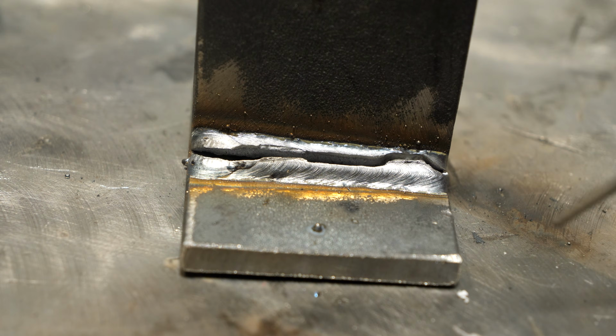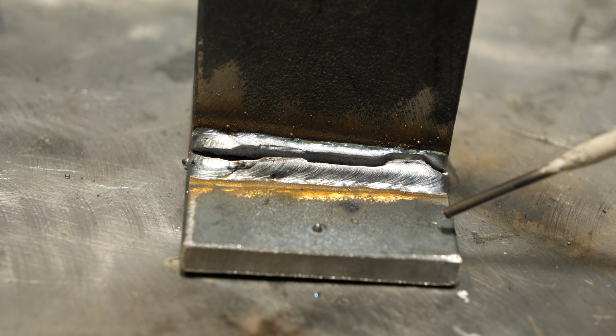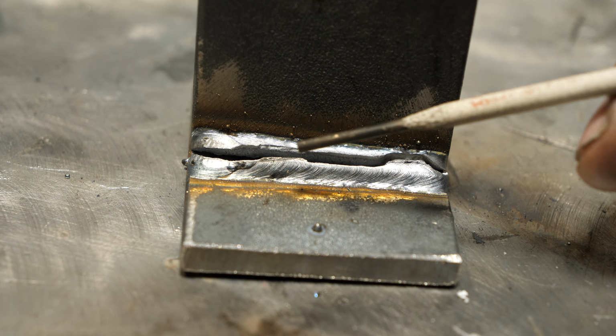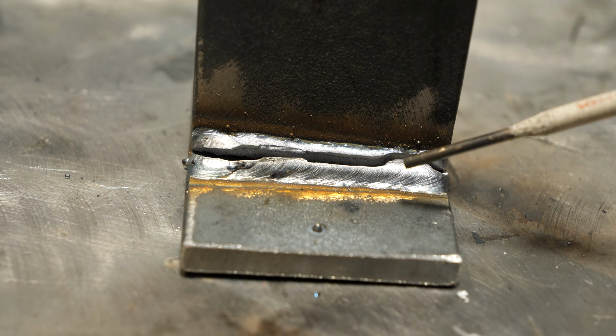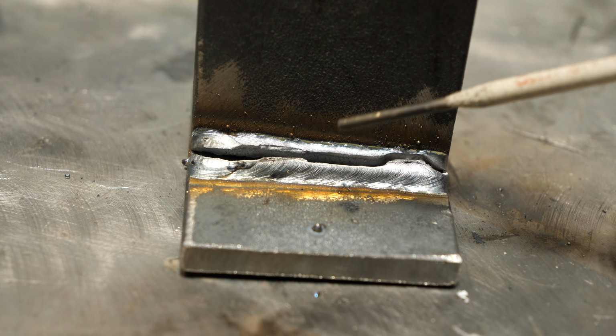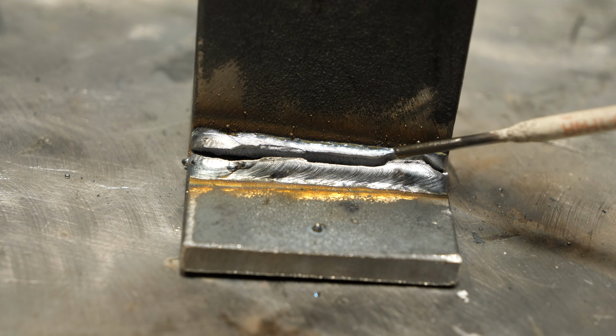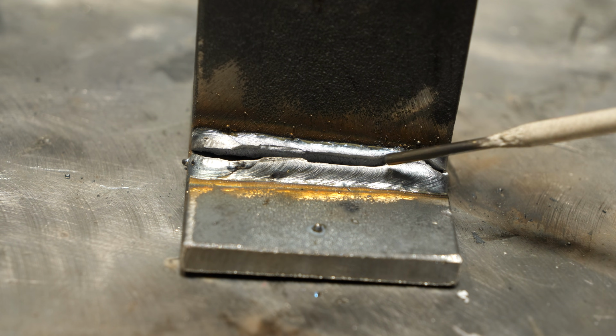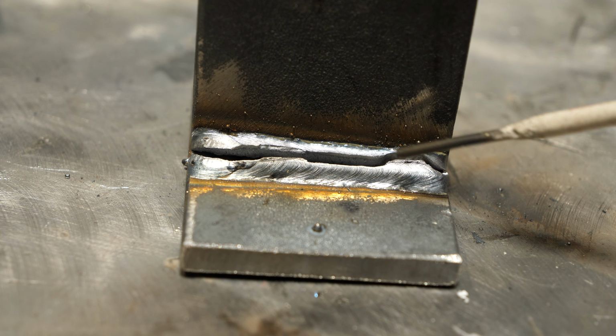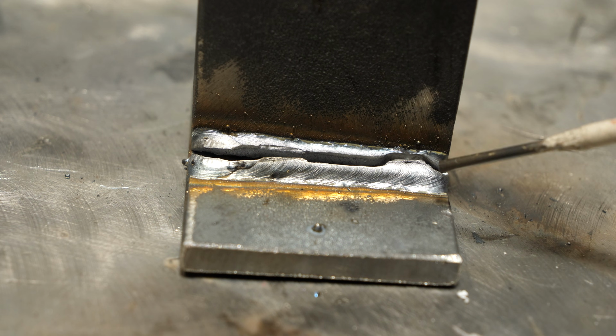Now let's look at the push. All right, so here's the push angle plate, and you can see better performance. The weld more or less broke down the middle of the plate instead of off of one side. And you can see this here where it broke off of this top plate. And if you've watched any of my videos, you probably already understand why. But this has a lot to do with cold starts with MIG. And by the way, this affects stick even more so. So you're not out of the woods with stick either.